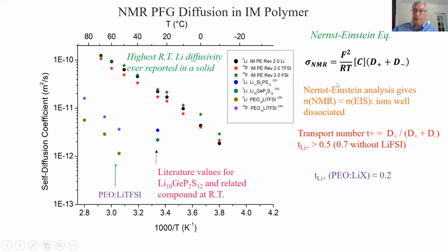Furthermore, by this so-called Nernst-Einstein equation, we can actually estimate the ionic conductivity, which we measure directly, but we estimate it, and we find that if you plug in the diffusion coefficients that we measure to this equation, we get about the same result that you measure. And that's very crucial, because that tells us that this salt that we put in this solid polymer is basically dissociated. The ions are free to move.